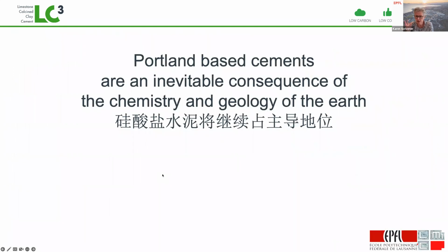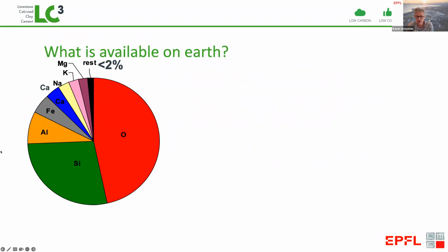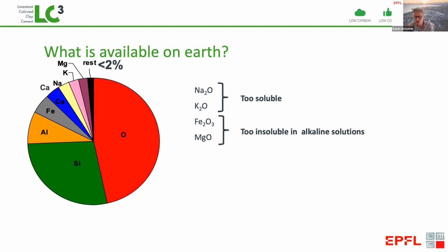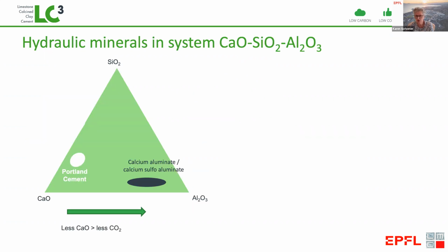So Portland cements are an inevitable consequence of the chemistry and geology of the earth. We see here that just 8 elements make up more than 98% of the composition of the earth. That's oxygen, silicon, aluminium, iron, calcium, sodium, potassium, magnesium. Now, the alkalis are basically too soluble. On the other hand, iron and magnesium oxide have too low solubility. So this means going from the whole composition of the earth, we come to a system of just 3 oxides, calcium, silica, and alumina, which we've studied for over 100 years.